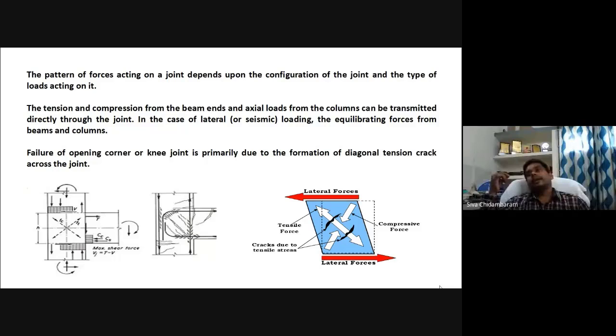So the crack starts to grow when the applied stress exceeds the tensile stress of the concrete, at every level of your RC elements. The crack will keep on growing. When you measure the stress at the tip of the crack, at the opened level of the crack, the tip of the crack will have a higher stress level compared to the bottommost crack region. This is called the stress intensity factor.